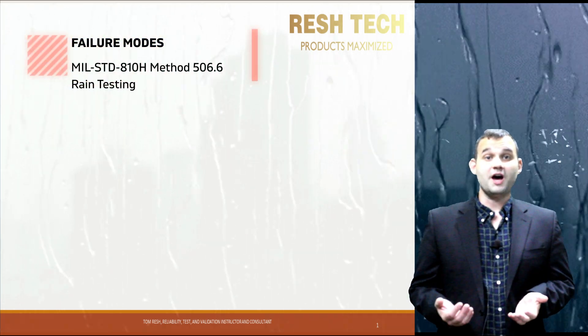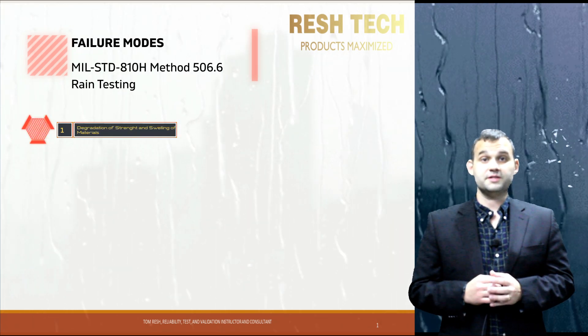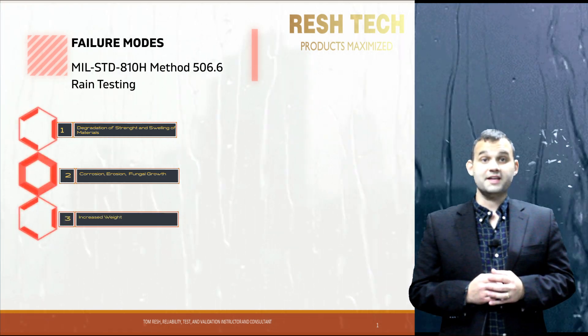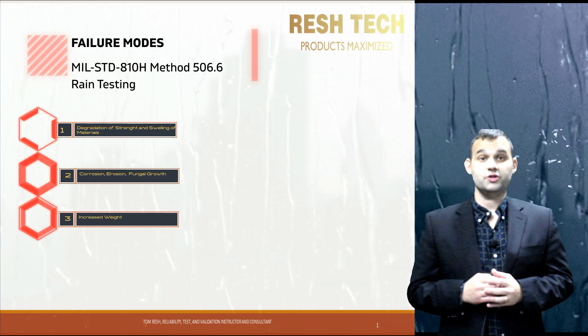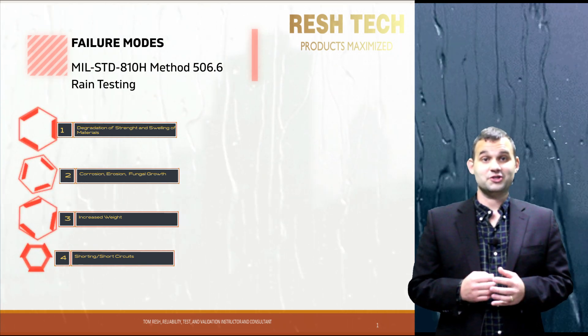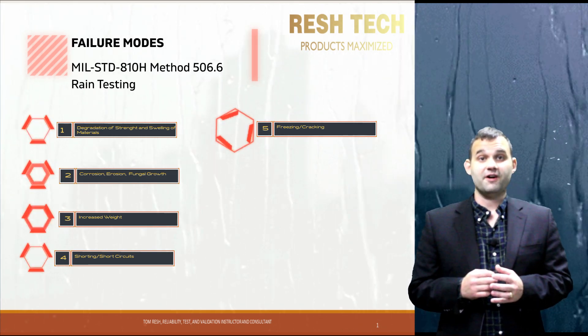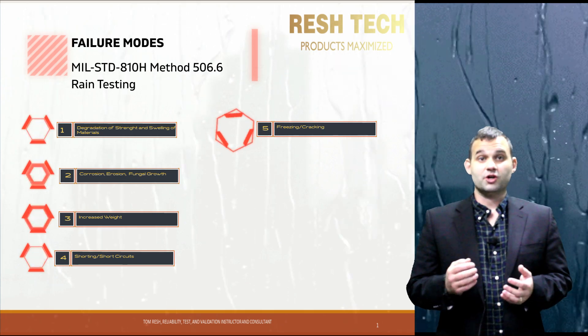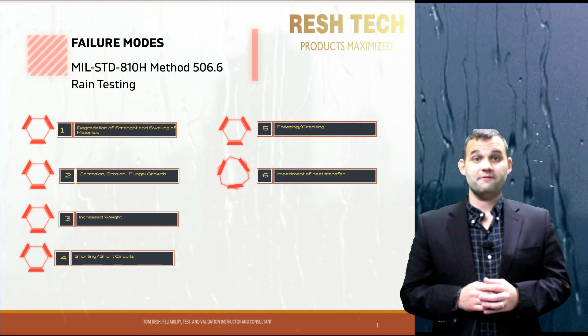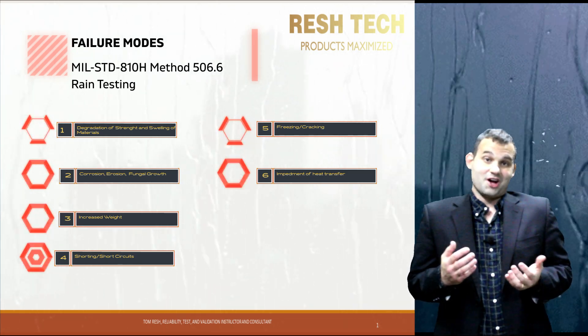Let's cover some failure modes to look out for with rain testing resulting from water ingress into your system: degraded strength or swelling of materials that react to moisture; increased corrosion potential; erosion or fungal growth; increased weight, which can cause catastrophic results depending on your system's use case; electrical or electronic apparatus becoming inoperable or unsafe due to shorting — fried circuits; freezing inside materials causing delayed deterioration and cracking in environments where liquid water is present during the day and freezing conditions occur at night; and modified thermal exchange, since water is an excellent conductor of heat and can impact heat transfer, and can also cause slow-burn conditions with propellants — obviously a recipe for disaster.